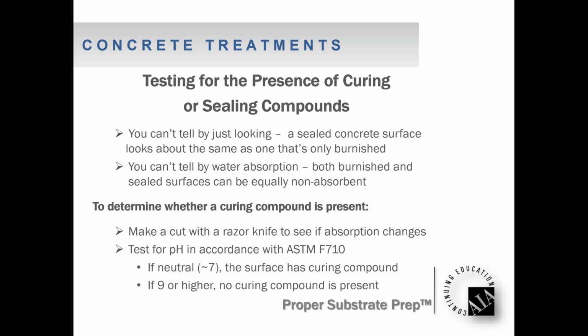All right, so I showed you all those pictures, and I asked you to take a mental note of those pictures because I want to get into how we do an evaluation here. And I wanted you to look at those pictures because I wanted to prove a point here. We can't just tell by looking at concrete whether it's been sealed with a curing compound, sealed with an acrylic sealer, burnished, and cover cured, because they all had a degree of absorbency. So you can't just tell by looking. We could pour water on it and do an evaluation, but I can tell you that cure and sealed concrete, concrete with a sealer on it, or polished concrete that's burnished, they all don't absorb water too well. So we can do a little bit different evaluation here.